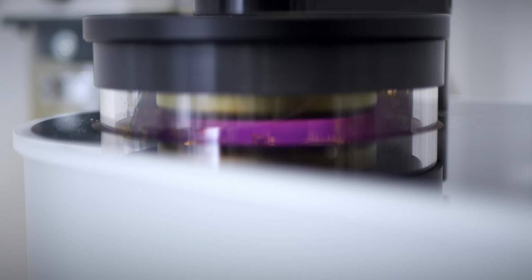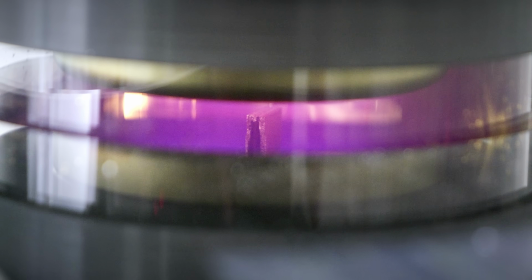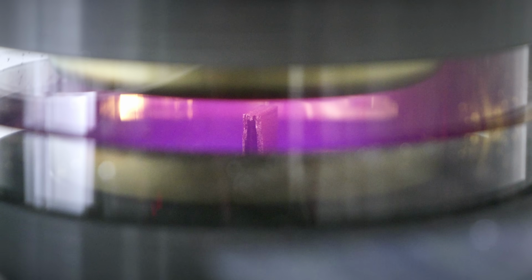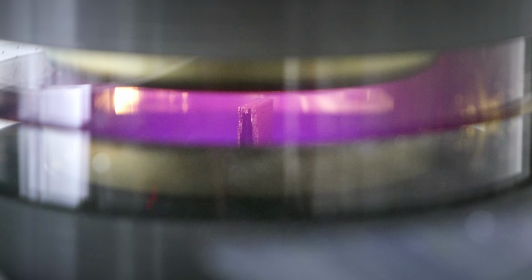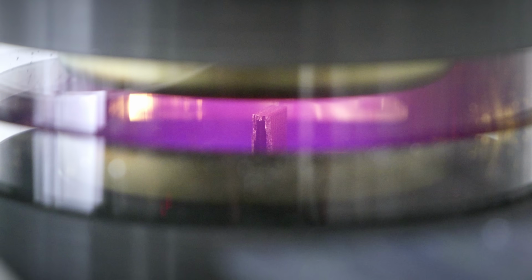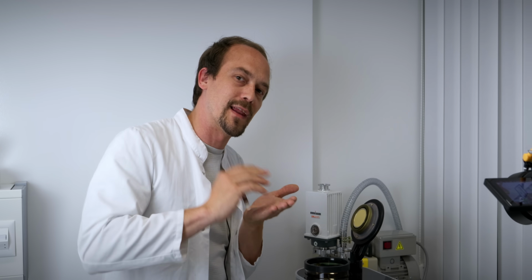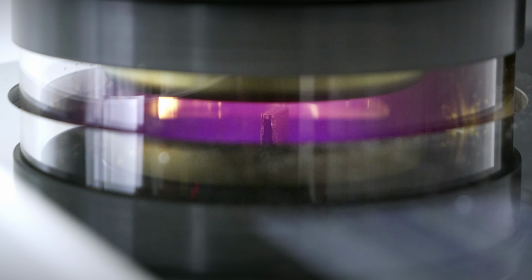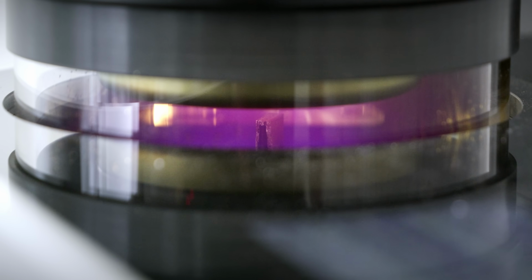What happens when I close that lid is we're pulling a vacuum down to nearly the vacuum of space. After that, a high current is applied and a little bit of inert gas is added. The gas atoms get excited and bump into each other and release energy that grabs gold particles from our gold plate, so they can fall onto our part and put a perfectly even conductive layer of gold on our part, just nanometers thin. So let's start this setup.